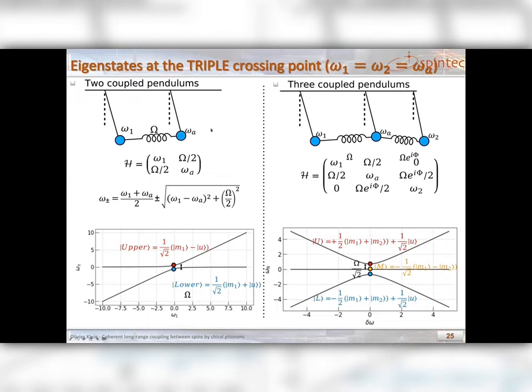We can think of our system as coupled pendulums. For simplicity, we first consider the case of two pendulums. The Hamiltonian looks like this, and we can easily obtain an analytical expression for the eigenfrequencies. So at the anti-crossing, there is a gap that appears of strength omega, which is the off-diagonal element of your Hamiltonian. The top branch is the out-of-phase coupled mode like this, and the lower branch is the in-phase mode.